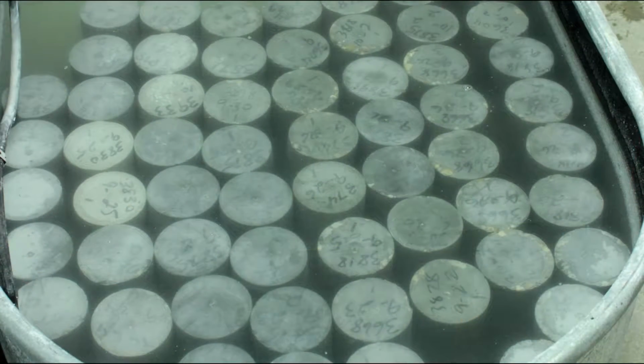Upon completion of initial curing, and within 30 minutes after removing molds, cure specimens with free water maintained on their surfaces at all times at a temperature of 73.5 plus or minus 3.5 degrees Fahrenheit using water storage tanks or moisture rooms complying with the requirements of specifications C511.